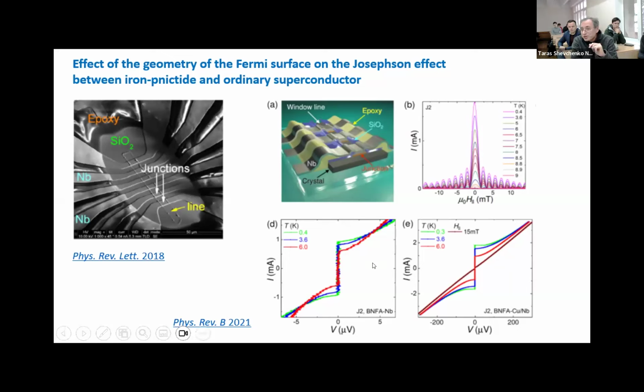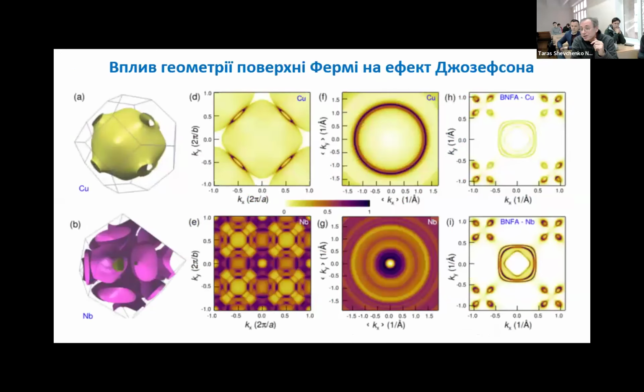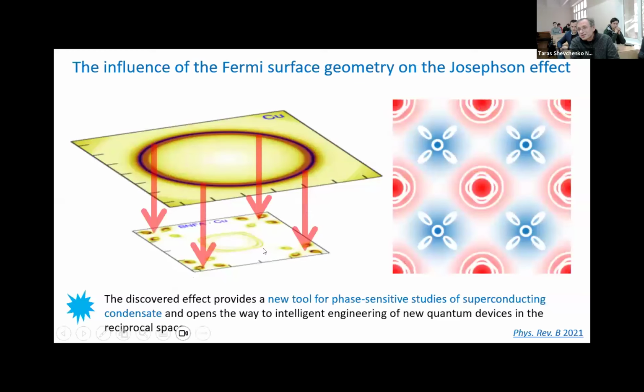destructive interference. But what is interesting, Alexei found that if he put a thin layer of copper in between niobium and the iron-based superconductor, he increased this parameter 40 times. And it was very unexpected because copper is not superconducting, and we didn't expect such a result, but later we understood it, because copper has such a Fermi surface. It is almost a circular Fermi surface, but it is a projected Fermi surface. It is like a circle, and this circle works like a filter,